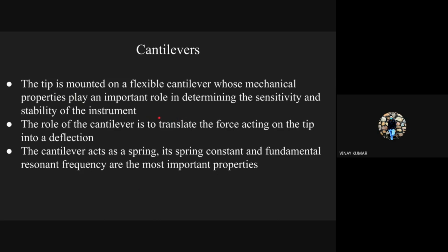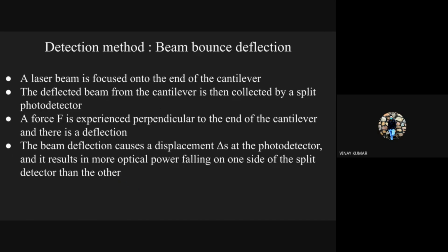The major role of the cantilever is to translate the force, the magnetic force in case of MFM, into deflection. It is basically a spring which obeys Hooke's law, and it has a certain spring constant and fundamental resonant frequency, which are the most important properties for the sensitivity of this technique.